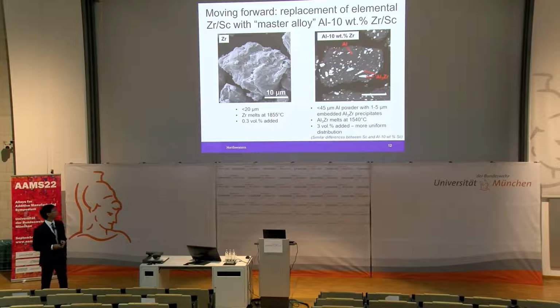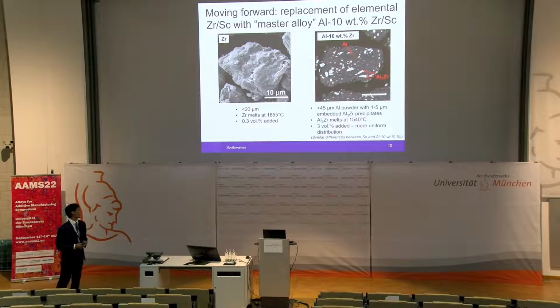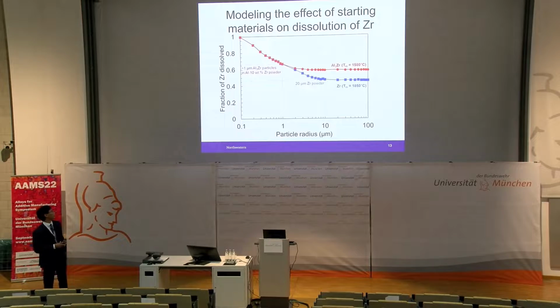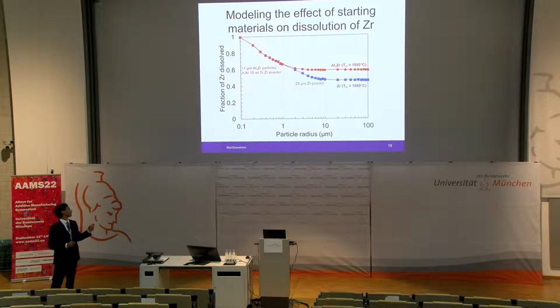Now you can see that the difference is that these aluminum 10% zirconium powders contain these micron-sized aluminum 3 zirconium precipitates, which are considerably smaller than the pure zirconium particle. We also know that the aluminum 3 zirconium phase also melts at a lower temperature, so this should also help our dissolution process. And indeed, when we revisit our model and model the effect of particle size and starting material on the fraction of zirconium that can be dissolved, we see qualitatively that there should be an effect by decreasing the powder particle size and lowering the melting point.